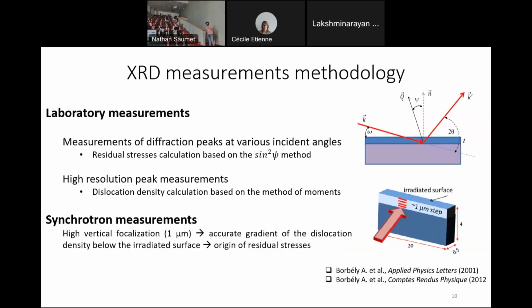doing XRD measurements. So two different kinds of measurements: laboratory measurements, where we are measuring the diffraction peaks at various incident angles in order to calculate the residual stresses below the surface, and synchrotron measurements, where we are doing measurements below the irradiated surface at 1 micron step in order to have an accurate gradient of the dislocation density below the irradiated surface.